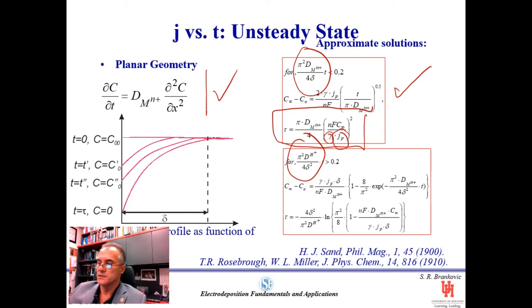If this term is bigger than 0.2, then we have a little bit more elaborate form of the mathematical description of the concentration at the interface as a function of time, and also a little bit more elaborate description of the transition time calculations. Yet what is important to appreciate here is that if we are defining any kind of a pulse current deposition process, which is a very common approach to many deposition practices, having a rough idea or calculations about what is the transition time in your system is a must.